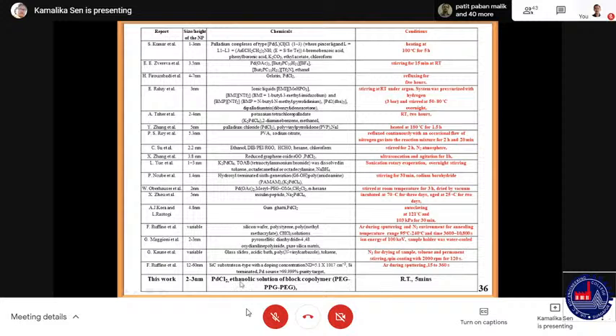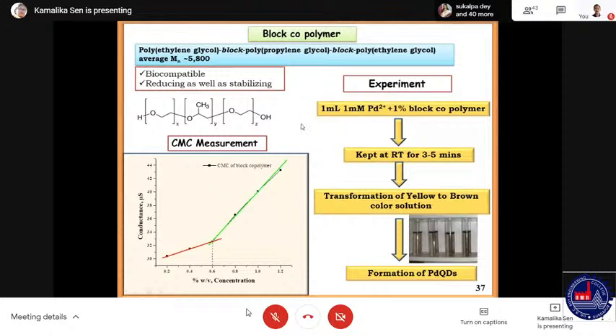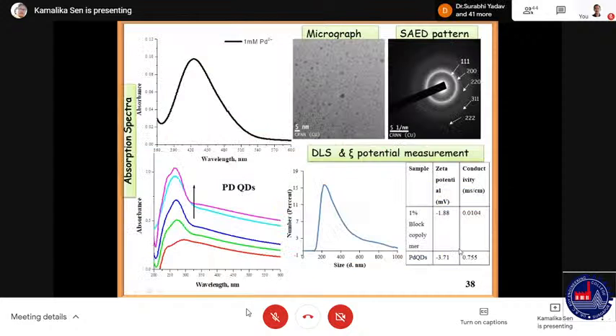But in this particular system, we need only 5 minutes at room temperature in presence of the block copolymer to produce the quantum dots. Actually, block copolymer generates micelles with only 0.6% weight by volume concentration, and the CMC can be measured by the conductance measurement. And if we take only 1 ml of 1 millimolar palladium 2 plus solution and add 1% block copolymer solution, keep it just for 3 to 5 minutes at room temperature, the color transforms from yellow to brown, and this is the visual change, and we can also see it using absorption spectra.